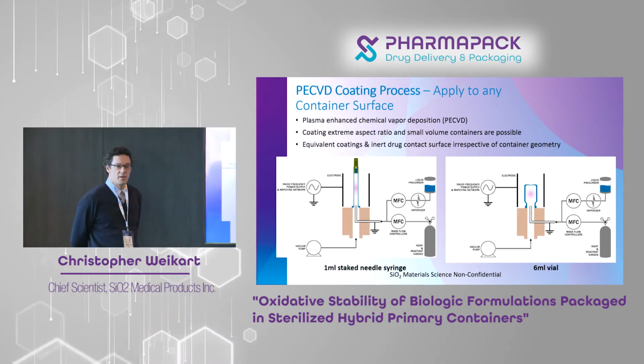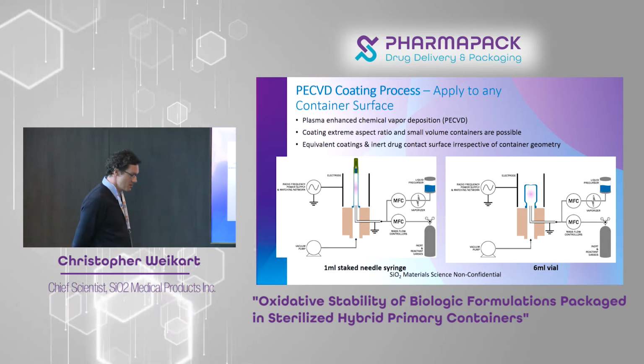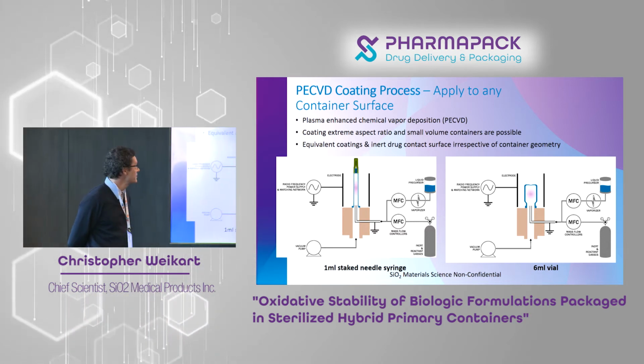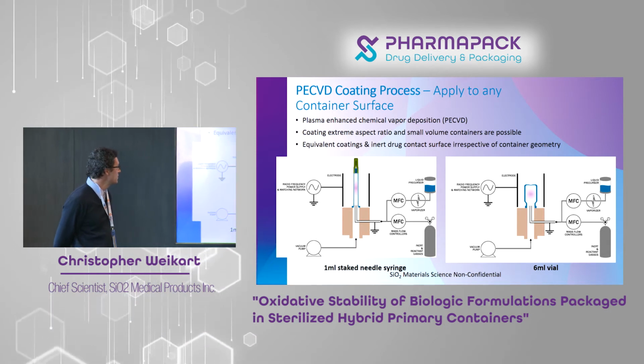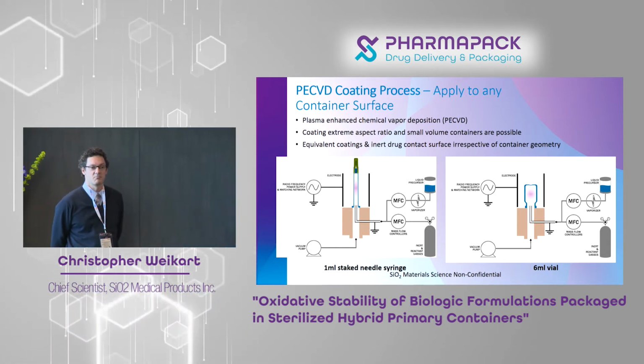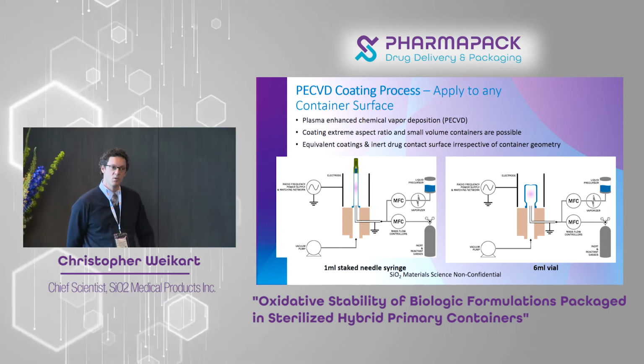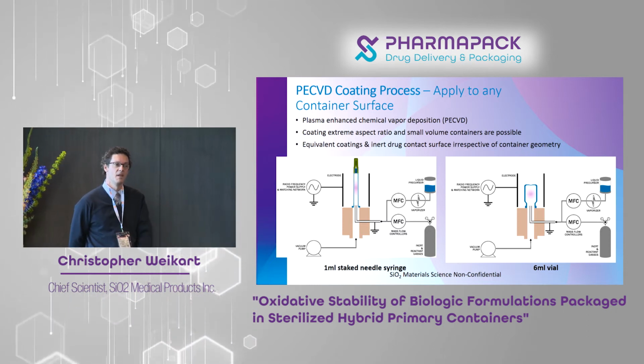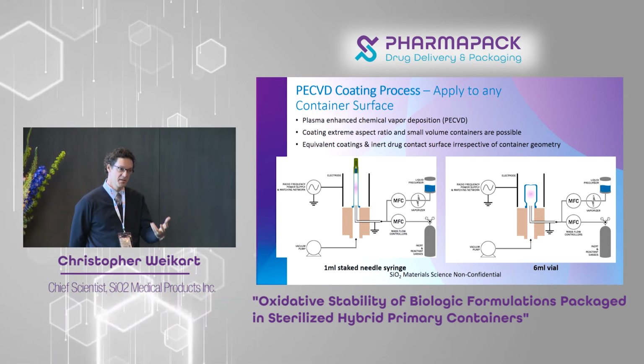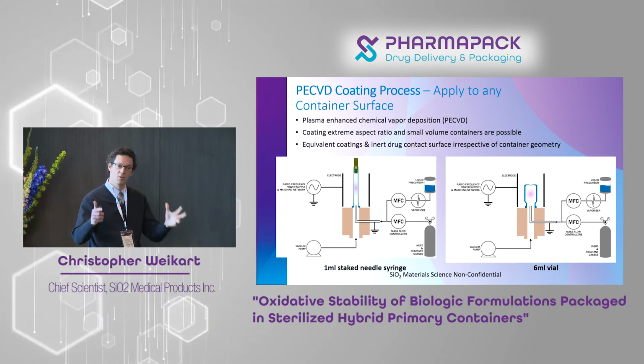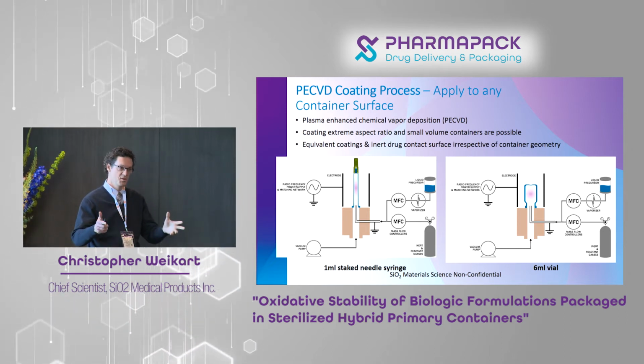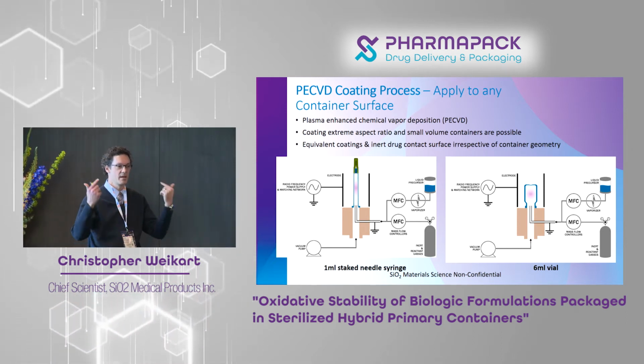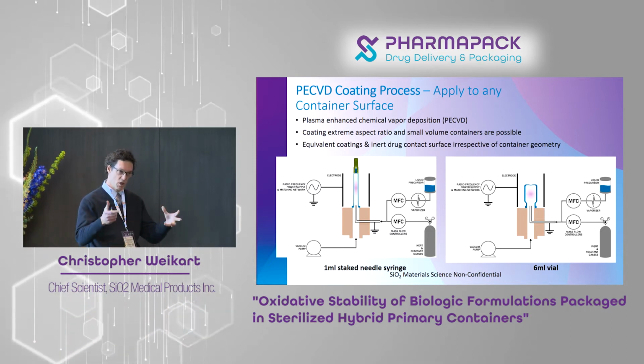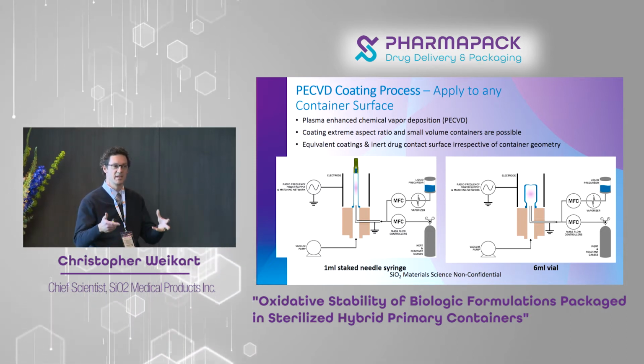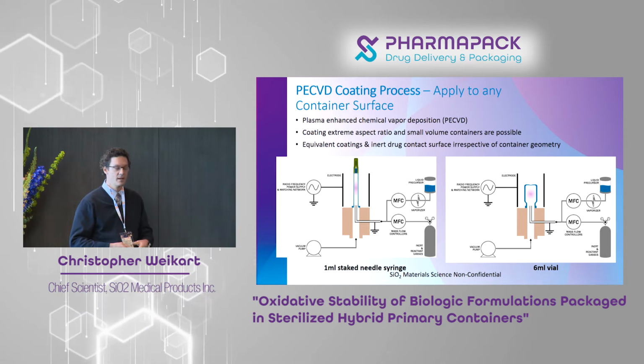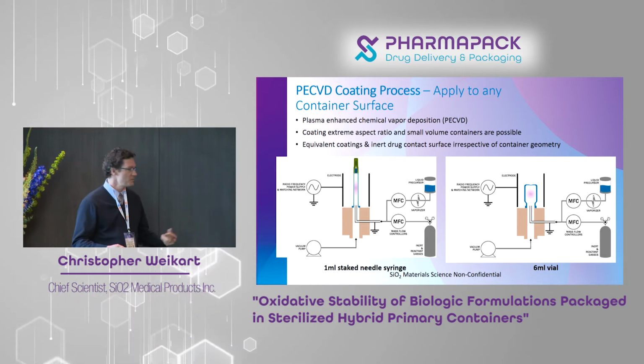And then you apply the coating. This is a process known as plasma-enhanced chemical vapor deposition. Essentially, we treat the part as a mini chamber. We remove the air from it using a pump, and we introduce a gas mixture to the interior. You apply a voltage across the part, and as soon as you do, it's like flipping on a light bulb. You get this glow on the inside. As soon as that happens, you're getting deposition of a coating. And it's a glass-like coating, as you'll see a little bit later.